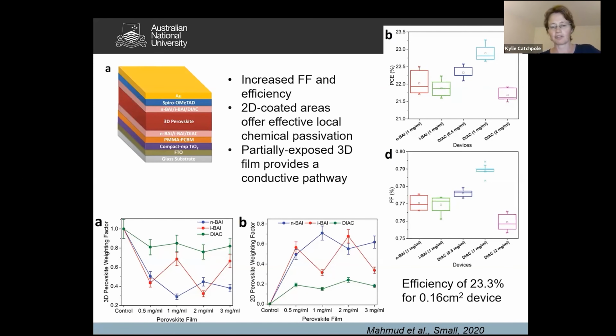And what we found using UPS measurements is that you have a change in the fraction of 3D perovskite that's on the surface and 2D perovskite that's on the surface. So especially with that dual layer, then you have more 3D perovskite on the surface and less 2D perovskite on the surface. So the overall net effect is that you have these 2D coated areas that give you effective local chemical passivation, but you also have this partially exposed 3D film to provide a conductive pathway.